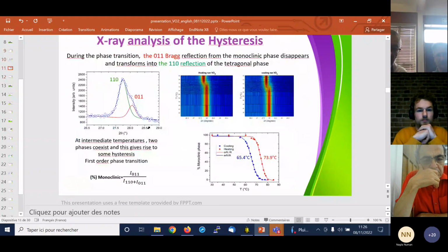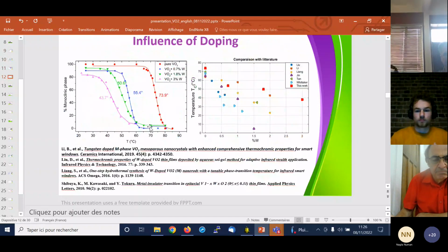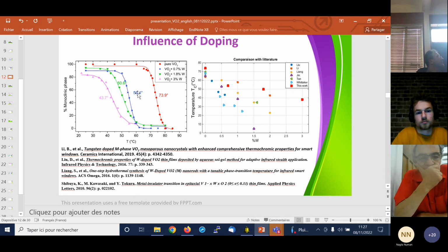Where is it? I didn't put it, or what? Yes, here. So if you look at this graph here, it's my pointer here. In this graph, you get the percentage of the monoclinic phase in the material. And if you look at the pure VO2, you see that you go from 0% to 100% of the monoclinic phase by using the calculation of the position and intensity of the 110 and 011 Bragg reflections. But if you do it for 3%, you see that you never go to 0% at high temperature, and you never go to 100% monoclinic phase when you are at low temperature.